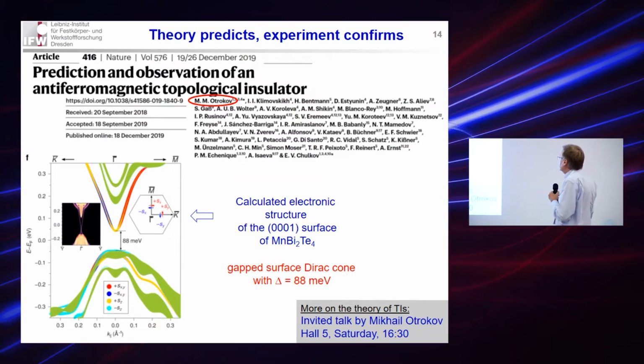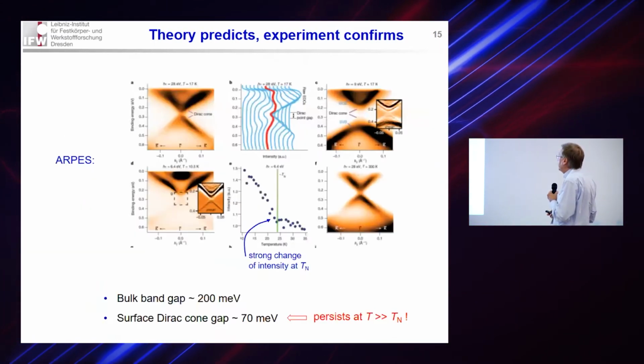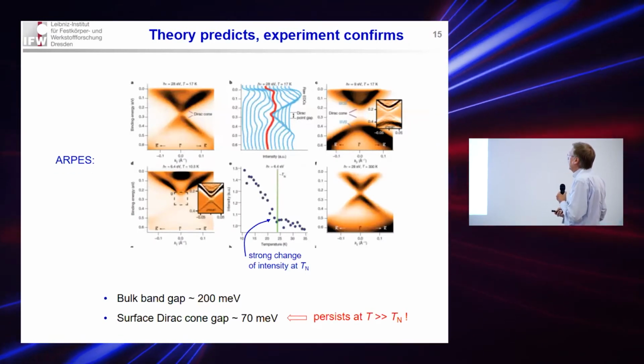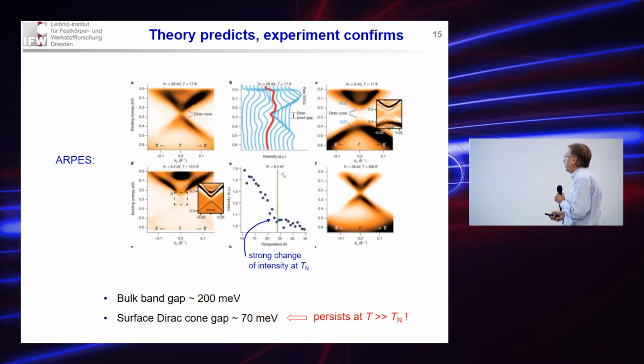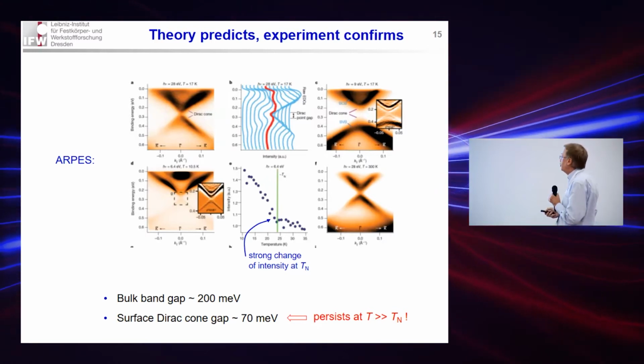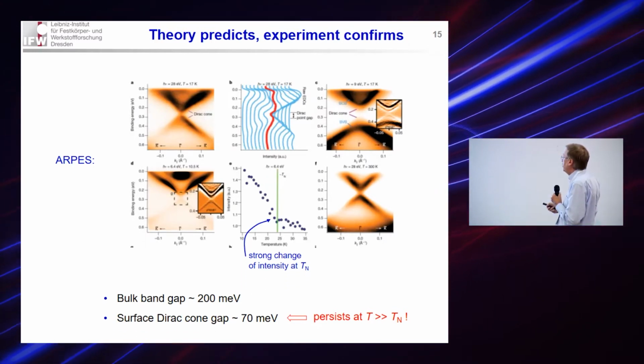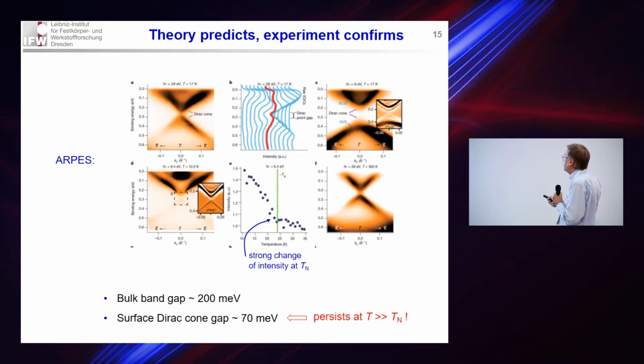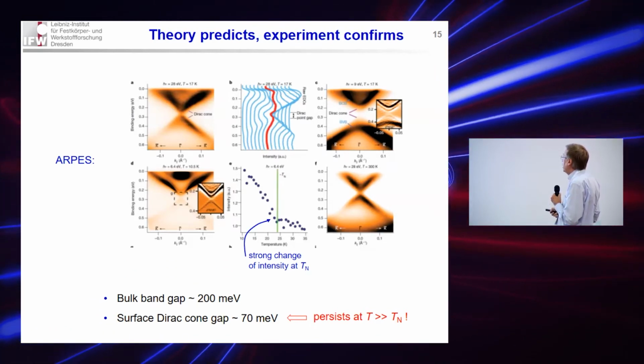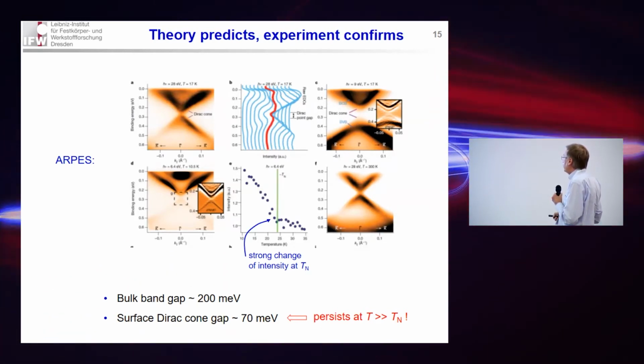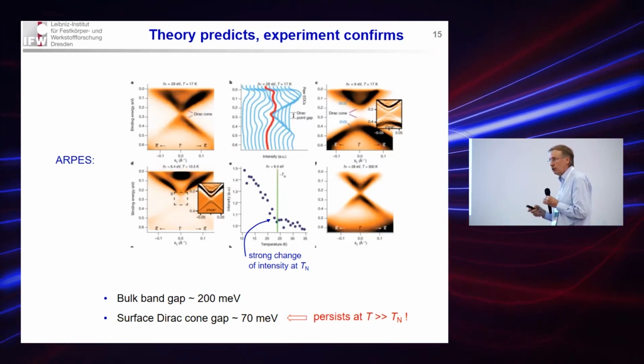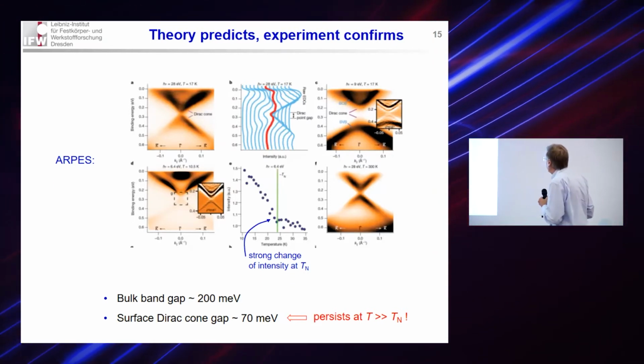So in this great collaboration of people, we of course looked for experimental evidence for this prediction, and indeed it was found in the ARPES experiments. There were found these Dirac cones at the surface state which are gapped, and the gap was about 70 millielectron volts, very close to the theoretical prediction.